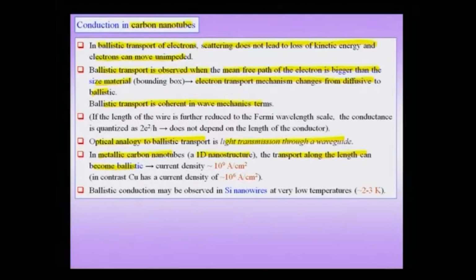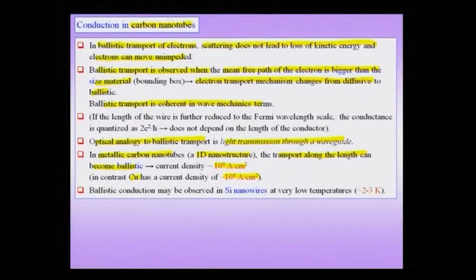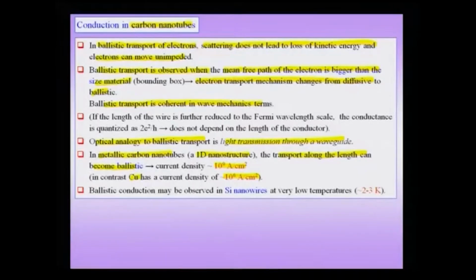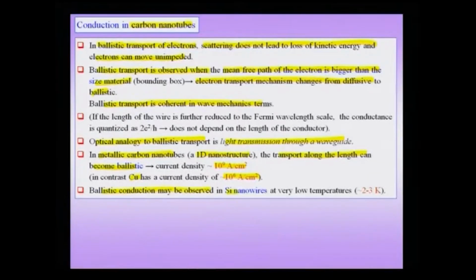And when this happens, you can have a current density of the order of about 10^9 ampere per centimeter square, and if you compare it with a metal like copper, which has a current density of 10^6, you can clearly see that this carbon nanotube has become a very good conductor along the length. We are talking about those kinds of chiralities, with M and N numbers, wherein you have what you call a metallic carbon nanotube. It is also seen that ballistic conduction may be observed in silicon nanowires at very low temperatures like 2 to 3 Kelvin, where phononic scattering becomes a small contributor.